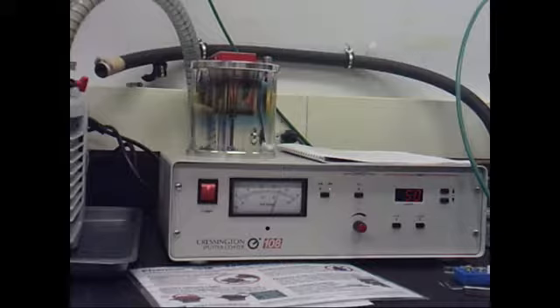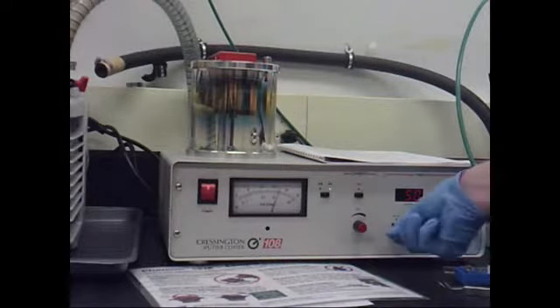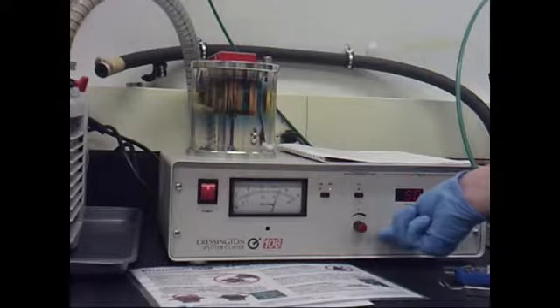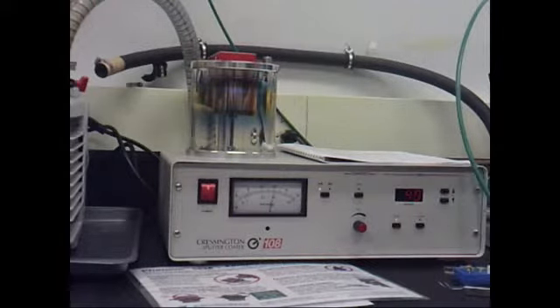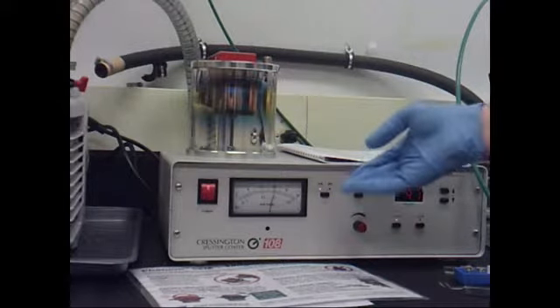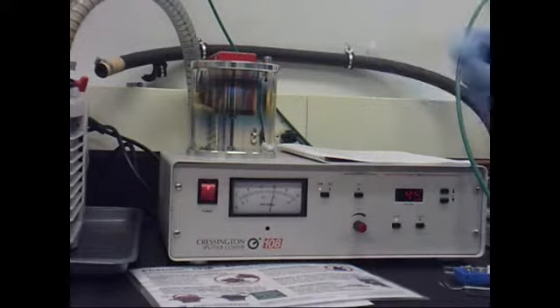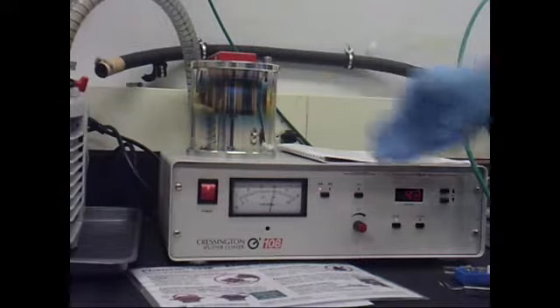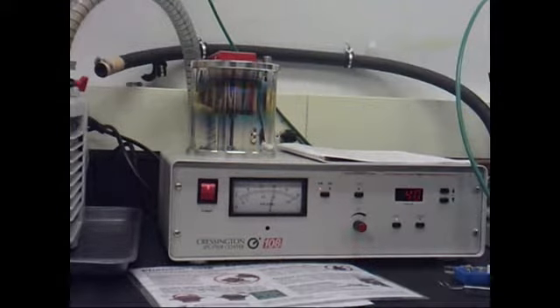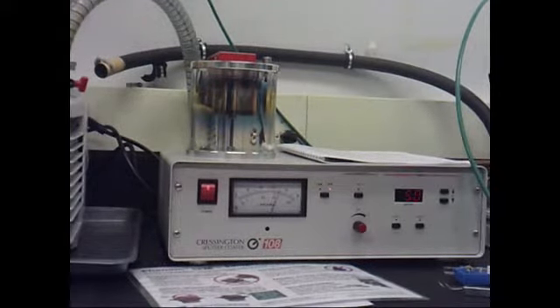So now that we've done our test, we can go ahead and start the sputtering process, and we do that by hitting the start button. You'll now see the switch change from millibars to milliamps, and your sputtering process is underway, as indicated by the timer going down and by the plasma which has been successfully struck. The sputtering process is complete, as indicated by the timer resetting and the gauge turning back to millibars, and by the plasma turning itself off.